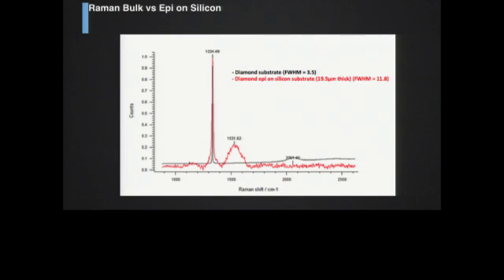These are some Raman measurements on foreign substrates. So this is on a silicon substrate, and this background here is just the diamond to give you an idea of this little additional graphitic peak here that's present in the epitaxial growth of diamond on silicon. The full width at half max is not quite the same as that of a high quality diamond film.